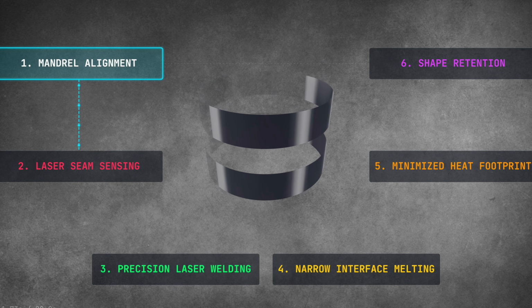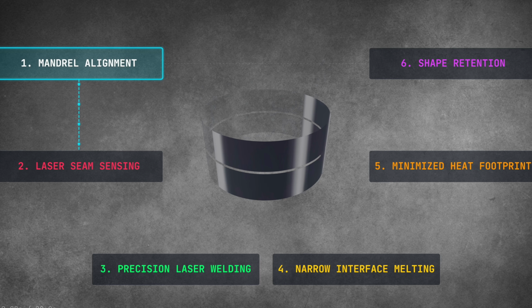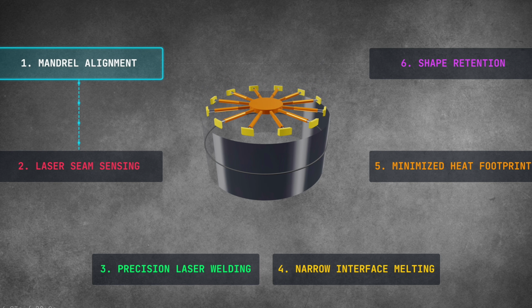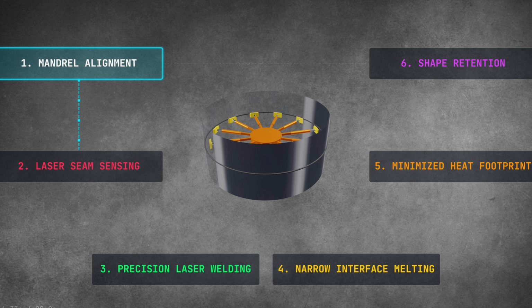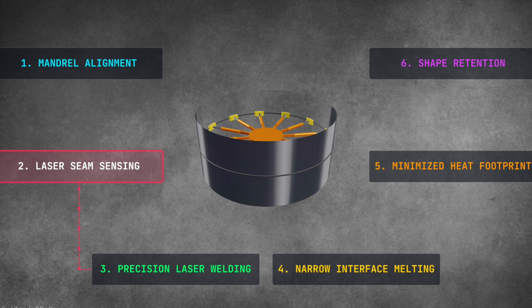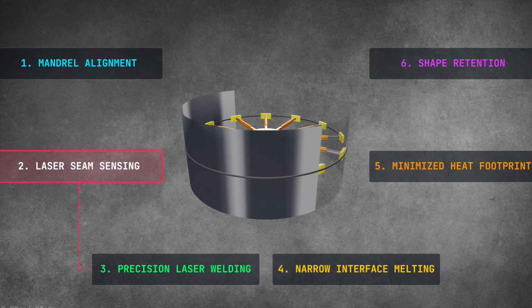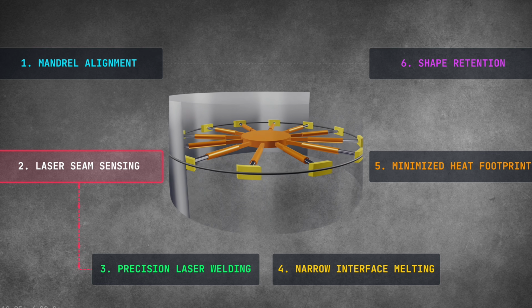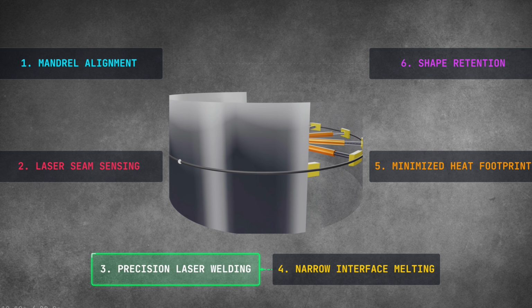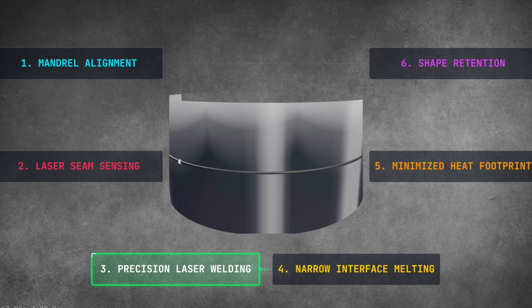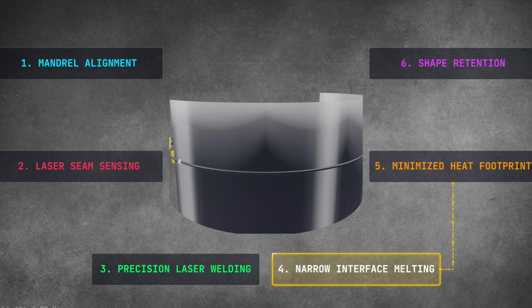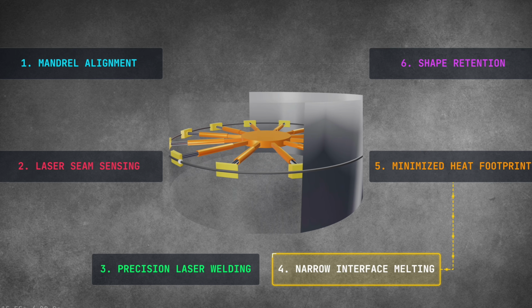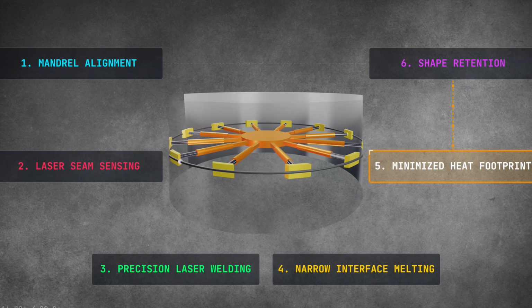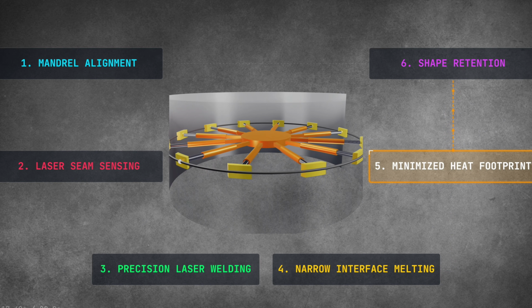Analyzing the complete process reveals how these subsystems reinforce each other. The mandrel's mechanical alignment enables the laser triangulation sensor to track the joint. This precise tracking allows the laser to weld exactly at the joint interface. Melting only this narrow interface limits the heat-affected zone. By keeping the thermal footprint small, the steel avoids buckling, maintaining the perfect circular shape achieved by the mandrel.